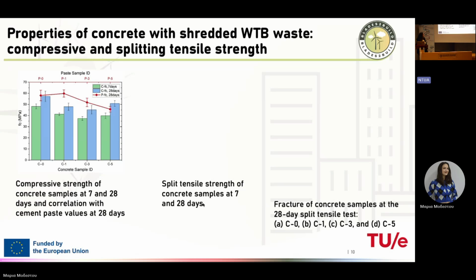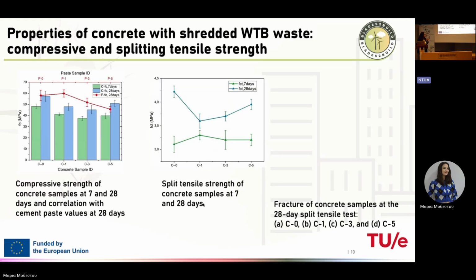For hardened concrete, we tested compressive strengths at 7 and 28 days and correlated with cement paste. So here is the red line. This is cement paste for the same dosage of wind turbine blade waste. And the green bars are 7 days compressive strength, and the blue bars are 28 days. So you can see that in compression, relative to cement paste and concrete, we have a significant, not high, but still some decrease in compressive strength.